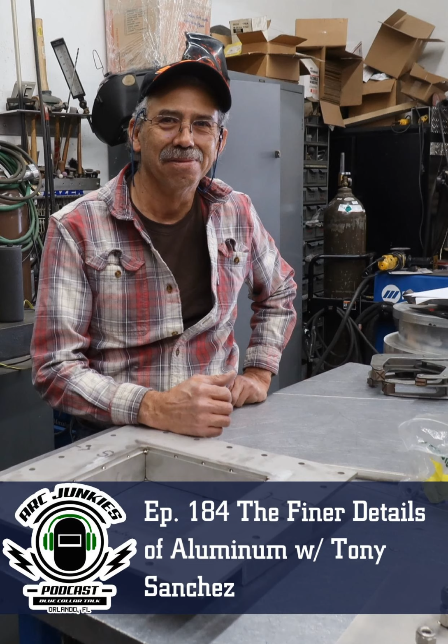Okay. So back to keeping your flutes clean: you put a little bit of that on and carve out the majority of it. Now in that repair, you're going to load that soft aluminum up into that carbide. If it's sharp, that carbide flips it good, but once it starts dulling, it holds it. So what I usually do is have a heavy aluminum block right there to the side, and a lot of times I've got it clamped. Once that carbide loads up, I'll run it on that cold, heavy aluminum block. It'll knock them out, because of the temperature difference. Then you put your beeswax back on it and start carving again.